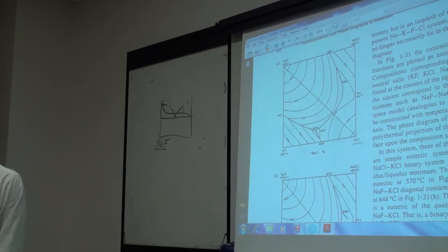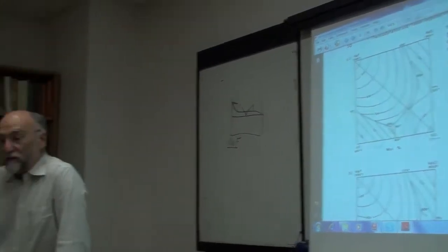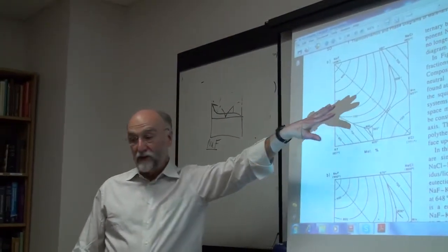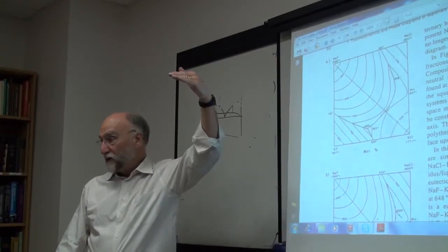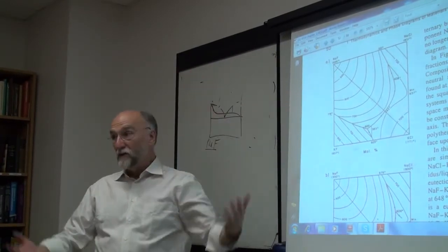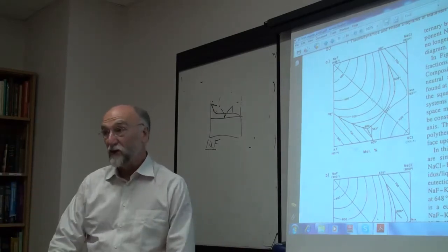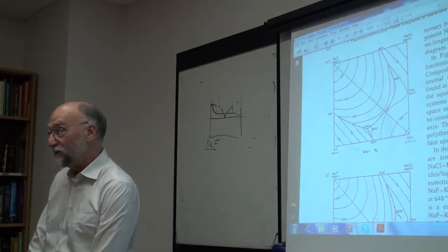So if you put an unnecessary restriction on the system, or an incorrect restriction, in this case a restriction of forcing it to be an ideal mixture, this will always give you too big a Gibbs energy. Every time you remove a constraint, the system gets another chance to lower its Gibbs energy. It's always trying to lower its Gibbs energy.